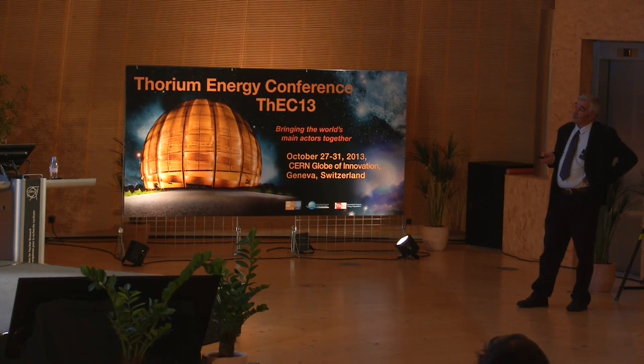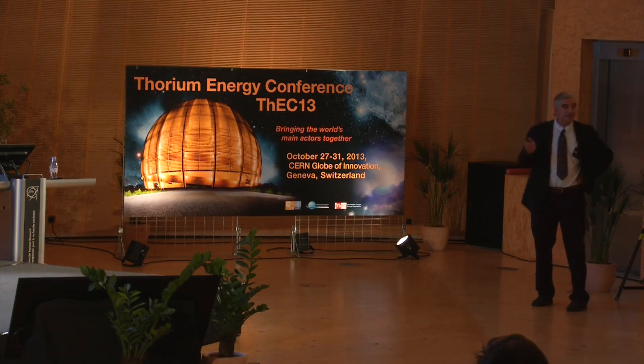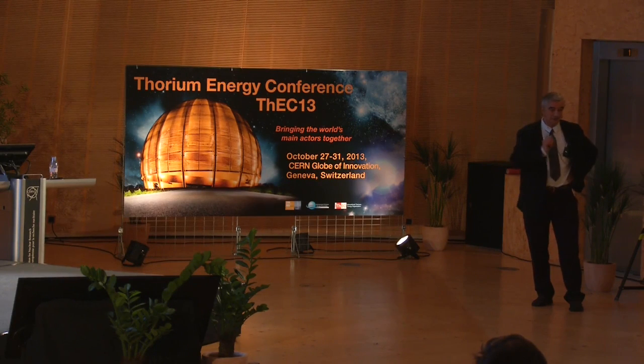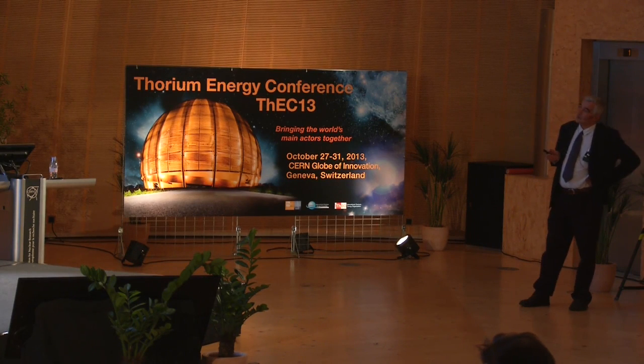Okay, so there was a round-robin test in order to prepare the laboratories to have common approaches for the characterization. After that, before preparing the samples, there was a segregation of LBE. There was an oven to melt the LBE. And then you can see here a slice before and after melting.